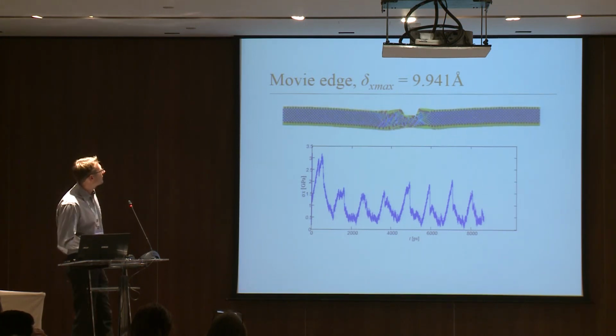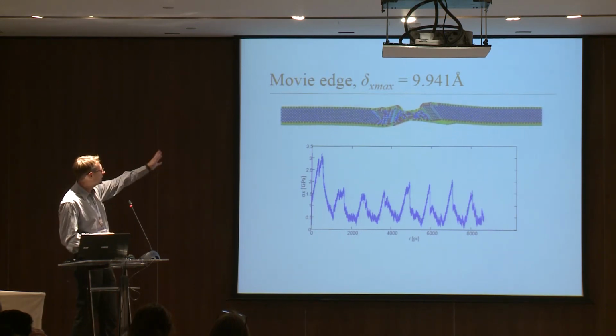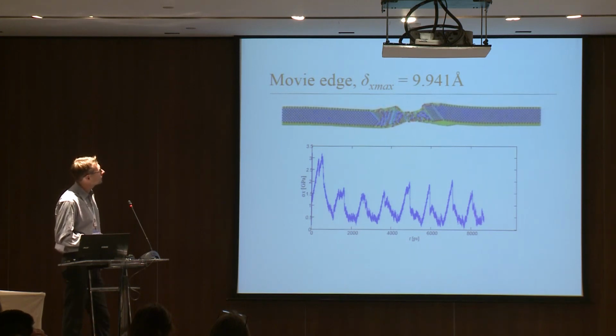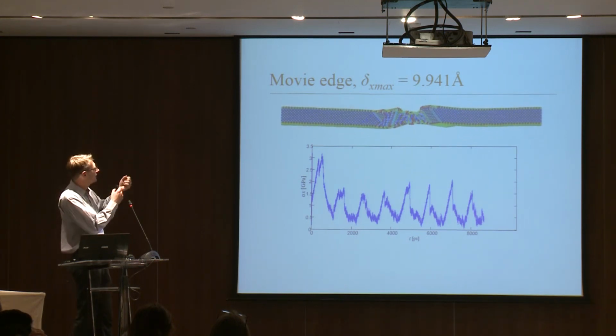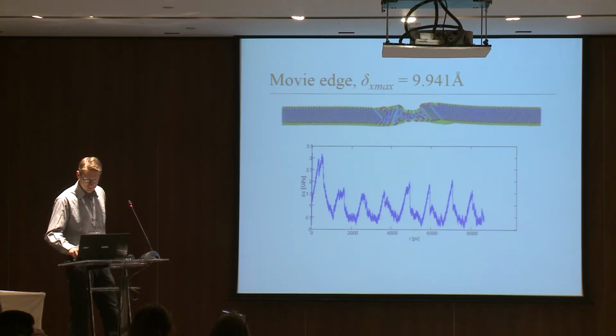With the edge defect, we can see that the plasticity is quite close to the defect, and we could see there that it almost broke after the second load cycle, but it could heal again and can withstand up to 8 load cycles before it breaks.